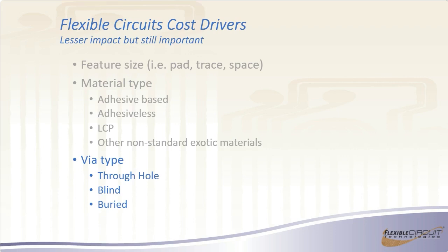As far as via types, we could spend an hour going through that, but just as quickly, keep in mind that every unique via structure that you have in your board will have a cost associated with it. If you have through holes, that's one via structure. If you have a blind via coming from 1 to 2, that's a second via structure. If you have blind vias from your bottom layer up 1, that's a third. Buried vias inside are unique. Even if you have 3 buried vias, but they're not in the same layers, they're each a unique via structure, and each of those will have a cost associated with it. So anything you can do to eliminate as many unique types of via structures as you can will help you with the cost of your flex.